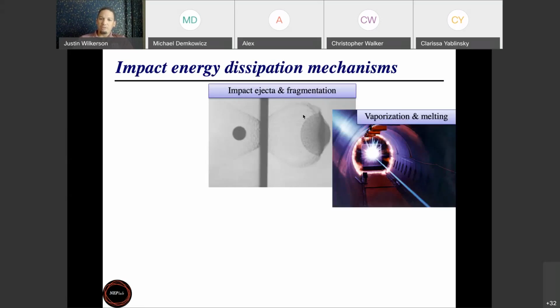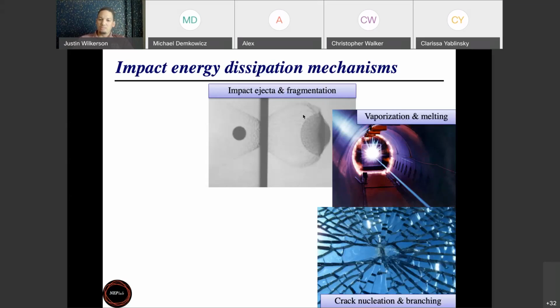If you hit these things at incredibly high velocities, you can get vaporization and melting. That's not going to be the focus of the talk here. We're going to stay at lower regimes where fragmentation and failure is the most interesting phenomenon. If the target material is brittle that you're fired into, then you'll tend to get brittle failure modes. And that typically consists of brittle cracking. You can have crack nucleation. You can have crack branching, where a single crack will split out into multiple cracks. And then you can have fragmentation as well, which we'll briefly talk about at the end of this talk.